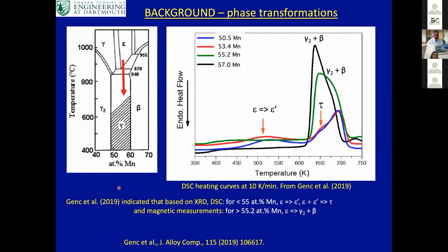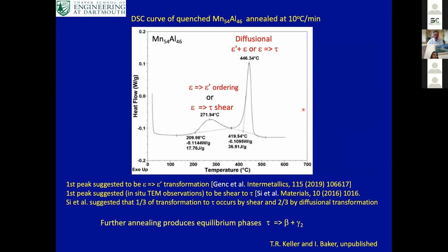This is some work by Genc and co-workers, where they looked at four different compositions of manganese aluminum, and you can group them into two parts, the ones that have manganese less than 55% and those of greater than 55%. So for the low manganese ones, this is a differential scanning calorimeter curve. You can see this low temperature peak here, which the author suggested is the change from epsilon to this epsilon dash, this ordering transformation. And then as you continue to heat the material, you then transform to the tau phase, which is this peak over here. For higher manganese contents, you don't see these low temperature peaks, and the material actually simply transforms to the equilibrium phases in the material. We've actually done a little bit of work on this as well.